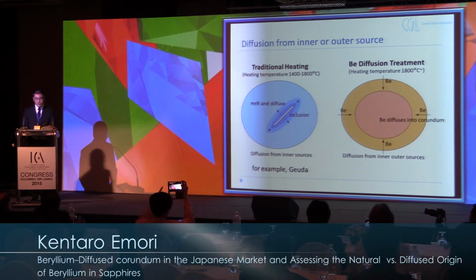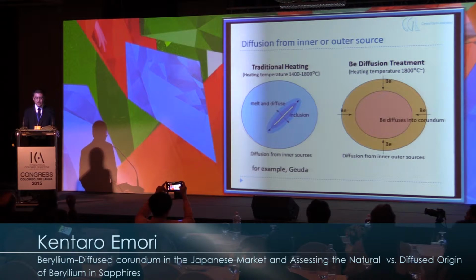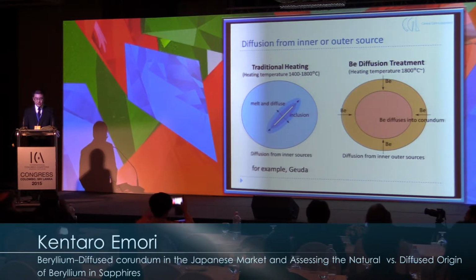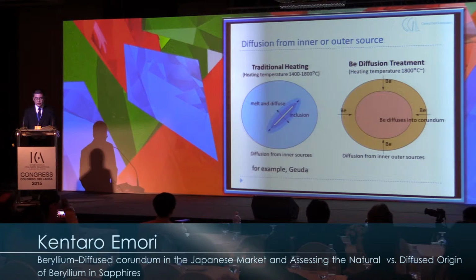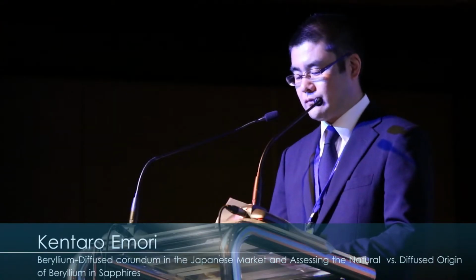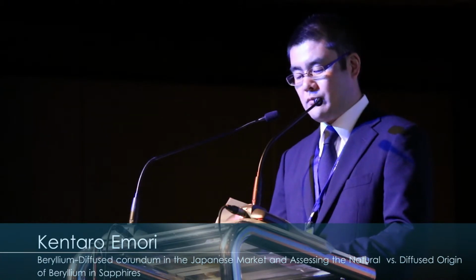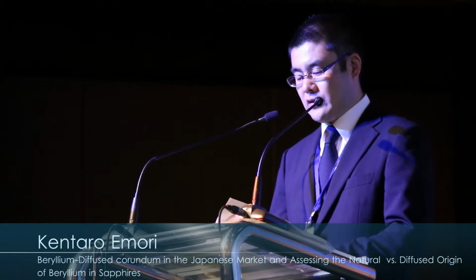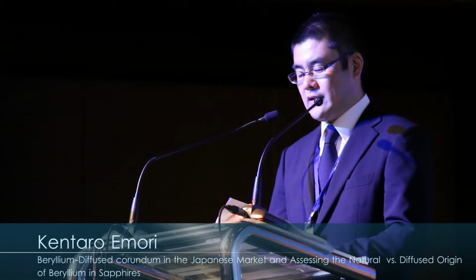Here is an explanation of the difference between traditional heat treatment and beryllium diffusion treatment. The left figure shows a schematic drawing of the traditional heat treatment. Under the heat treatment, an inclusion in corundum melts and elements included in it diffuse into corundum. This heating is done at 1400 to 1800 degrees of temperature.